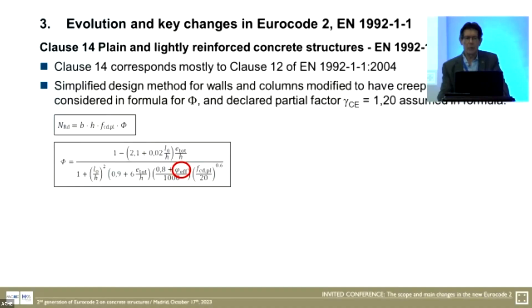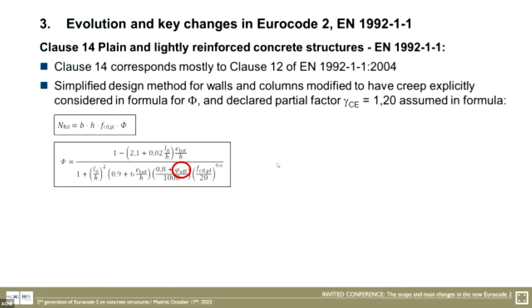Clause 14, plain and lightly reinforced concrete structures, is basically the same as we have today in clause 12. We have, however, changed slightly the coefficient phi for the simplified design method for walls and columns, because we wanted to have the effect of creep in these walls explicitly considered, so that countries who want to consider it can do it, and others who do not want to consider this can leave it. And we also wanted to have the partial factor, which is assumed in these provisions, clearly shown.